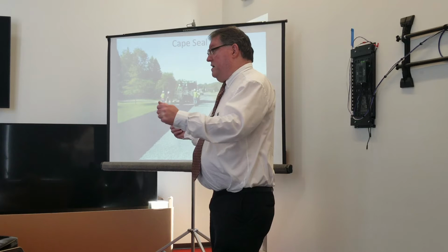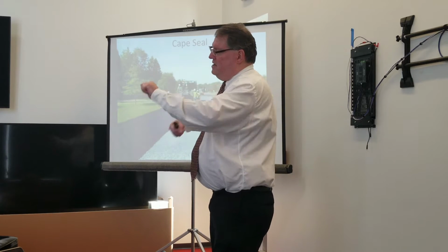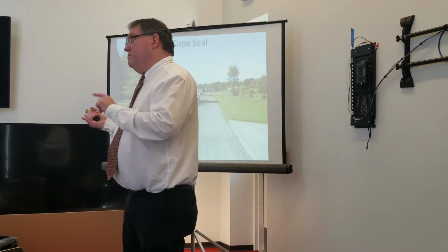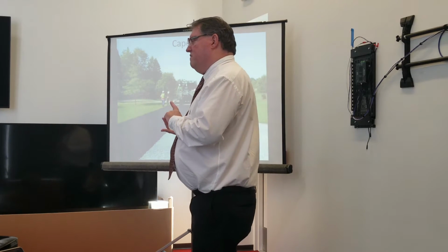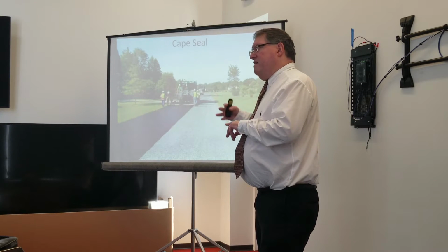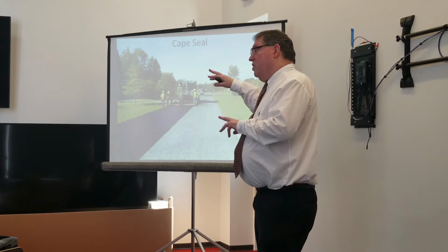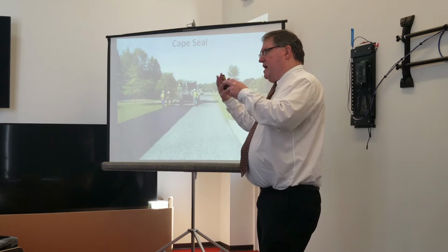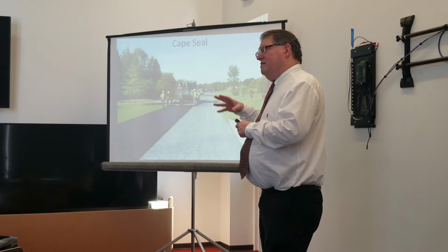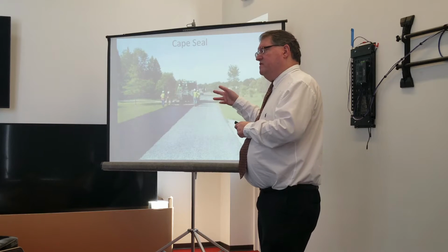But some of that was coming off the first year, and in fact, on a hot day, when you turned the tires without moving, what we call a power steering mark, where you're at the end of the driveway and you're cranking the wheel but you're not moving, we were getting those in that slurry a year after it was placed. That tells me there was a material problem, right? That should not happen. So if you're seeing a lot of early material loss, that may have been a problem specifically with that emulsion or with that mix design. You are going to lose a little bit of the fine material from the plowing, but if you're seeing a lot of material loss, that may be an issue specifically with that mix that was placed.